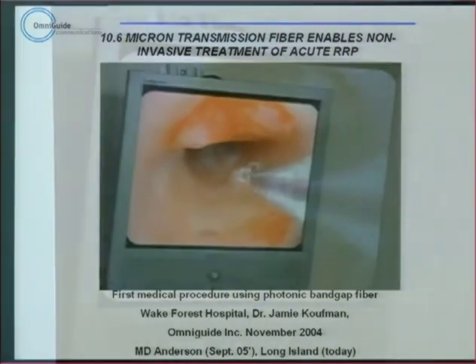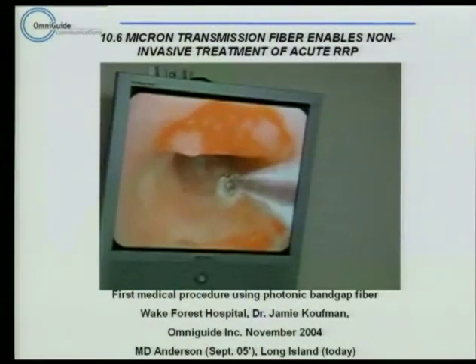This is the tip of a fiber, a little over a millimeter, going down through the nasal canal into the airways. There's about 10 or 15 up to 20 watts of CO2 laser energy going through the fiber and basically ablating the tumor. Now, this procedure was carried out by Dr. Jamie Kaufman at Wake Forest in North Carolina, and since then there has been full FDA approval, and procedures have been carried out at MD Anderson Cancer Center and actually today in Long Island.